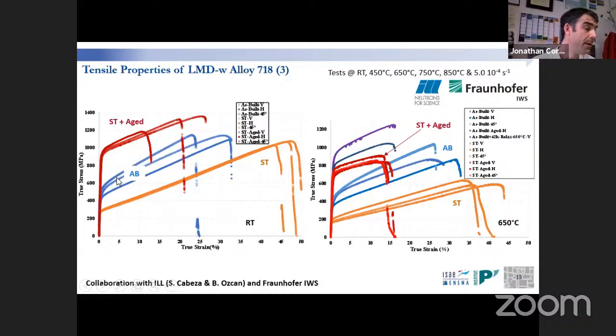So we have here in blue the as-built state for all the orientations, the solution treated state, and then solution treated plus aging, a typical aeronautic aging to trigger the precipitation of gamma prime and gamma double prime precipitates. Probably not the optimal one for this kind of process, but we know that we are improving the properties. What is really impressive, first of all, is that in the as-built state we have quite a high yield stress in comparison to the solution treated material, in which we have yield stresses of nearly 300, 350 MPa, which are really typical of solution treated cast and wrought 718. So no surprise on this.